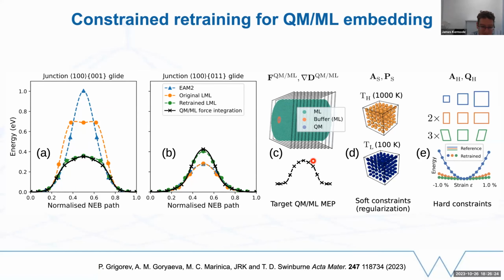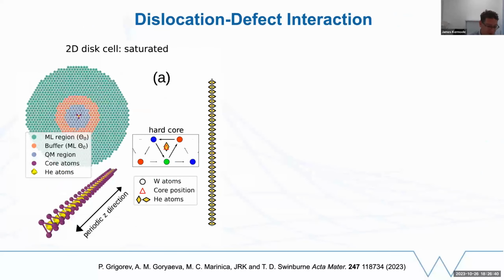So putting those three ingredients together and looking at a couple of different dislocations, you can see we move from the original potential in orange to the updated potential that really matches very well with the quantum mechanical targets for both of these dislocation glide processes. And that's great because it means we can then move to a three-dimensional setting. We can go from this 2D case where we're a bit artificially modeling, if we put a defect in, a whole long line of defects interacting across the periodic boundaries.